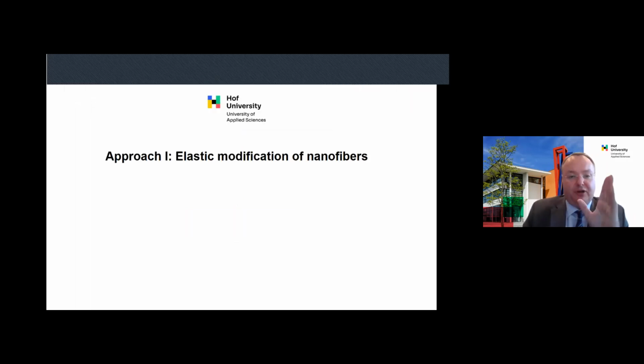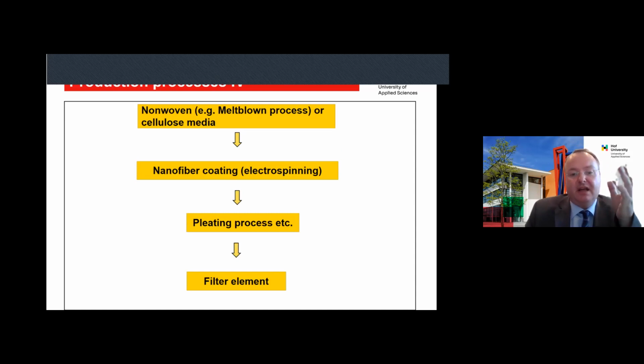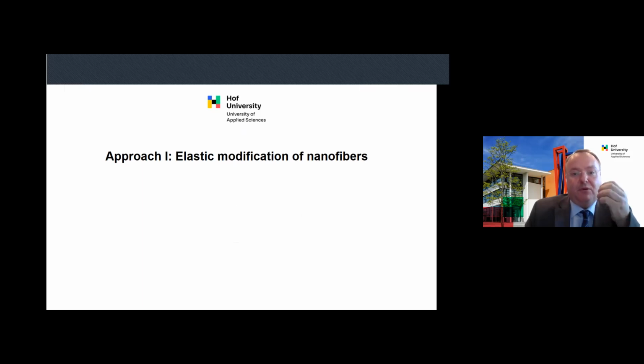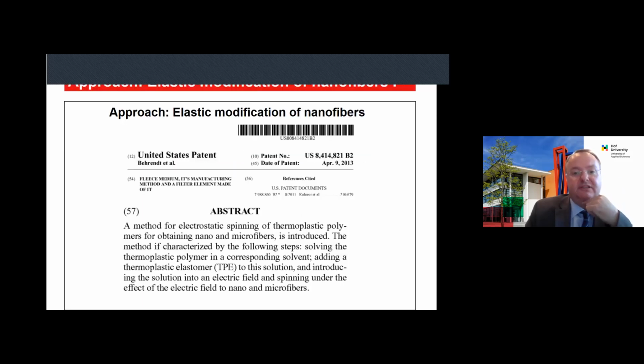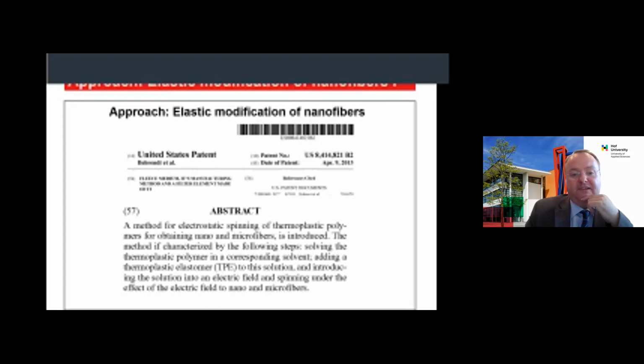Therefore, my first approach is the elastic modification of nanofibers. Now it's interesting for the experts. During the pleating process, when we create our folds, we have a high level of mechanical stress for the nanofibers, and we can improve this if we carry out an elastic modification of the nanofibers. Therefore I developed a method to increase the mechanical resistance of nanofiber webs by the implementation of thermoplastic elastomer domains or thermoplastic elastomer particles.